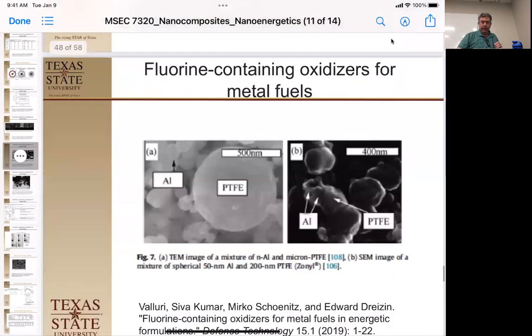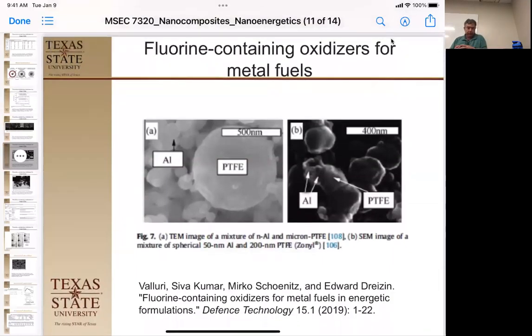Okay, all right, so then how can you do this with nano aluminum and micronized Teflon? If you just do a big chunk of Teflon and you have your nano aluminum in there, you need to have some intimate mix. So you can do the micron Teflon, or you can actually mill it because Teflon is soft enough to be milled. So in this case here, they actually brought a pre-milled 200 nanometer Teflon.